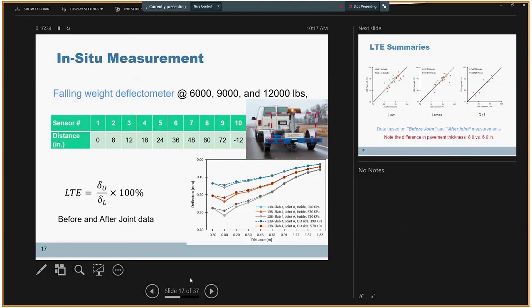The test was conducted at 3 load levels of 6, 9, and 12,000 pounds. And the test was conducted on different slabs from lower cementitious material and the reference cells, both the inside and outside lanes, exposed to traffic or not exposed to traffic. And the test was performed at different spots of the slabs. For all these spots, we got the data and developed the deflection basins, and based on the data obtained from testing the pavements before and after the joints, we determined the load transfer efficiencies for these concrete mixtures for these pavements.